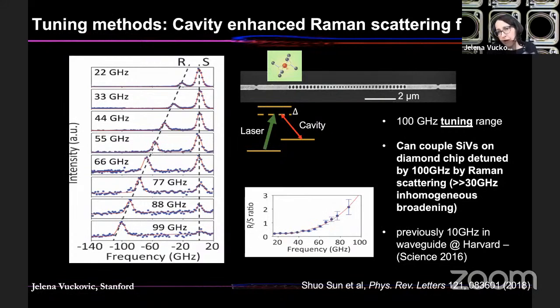But we have done it for color centers inside of the cavities. And you see that you can tune the frequency of the scattered photon, but the most important part is that you can tune it by up to 100 gigahertz. And as I mentioned previously, we have shown that we can grow color centers with 30 gigahertz inhomogeneous broadening, which means that by this technique, you can compensate for all of the inhomogeneous broadening between color centers.